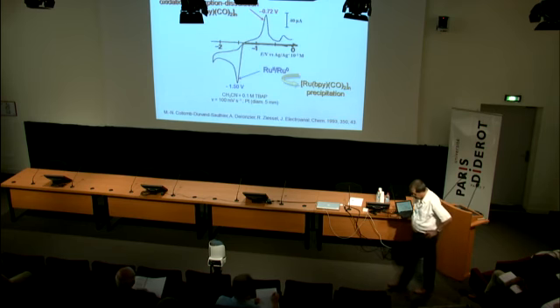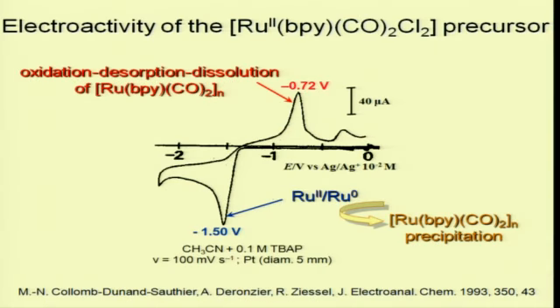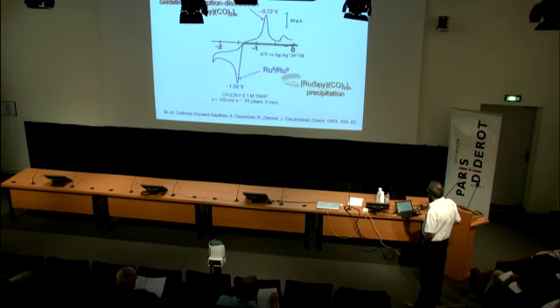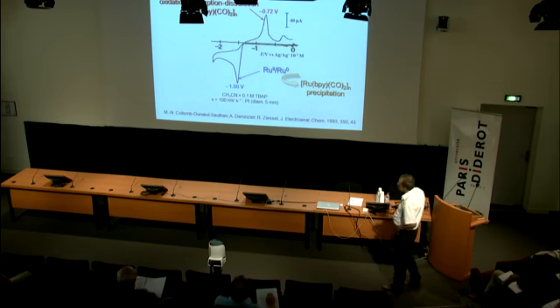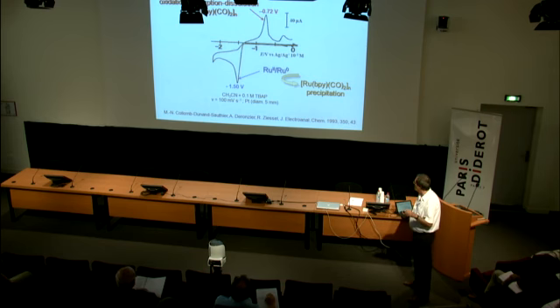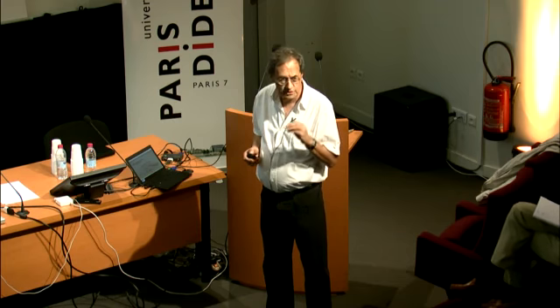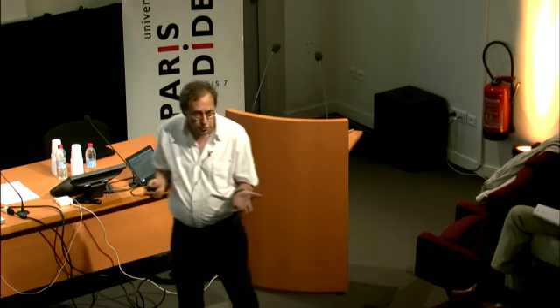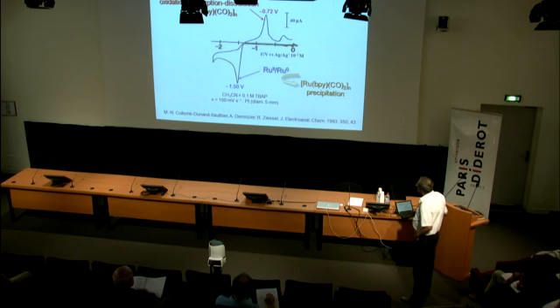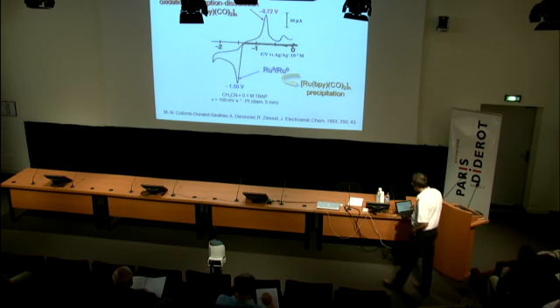Just as an illustration, look at the electroactivity of a precursor of that time, a bis-chloro derivative. It is in acetonitrile, that's the cyclic voltammogram here, corresponding to the reduction of the precursor. The signal here is typical of electrodeposition and redissolution of a compound on the electrode surface. It looks like, for instance, copper 2+. It's a two-electron process, as I said, with the formation of the polymer on the surface here. And when you go back, there is oxidation, desorption, and dissolution of the corresponding film.